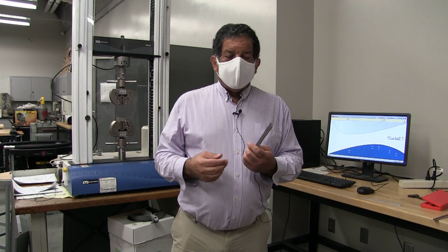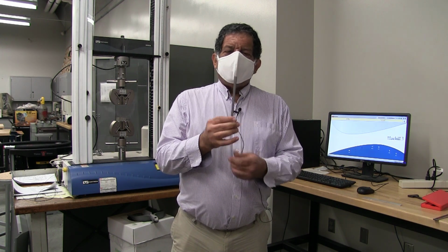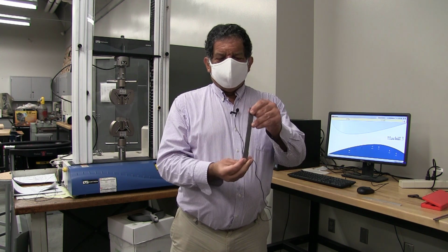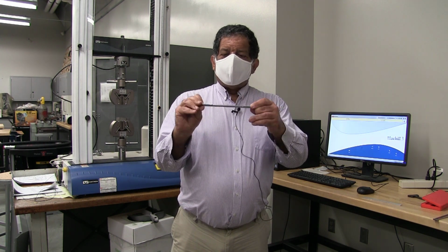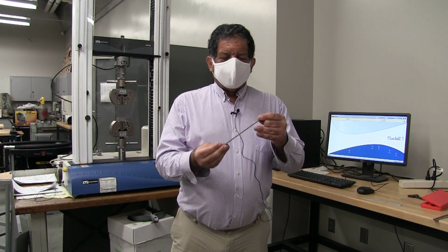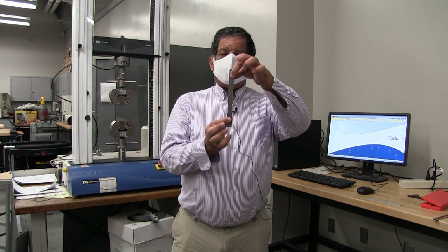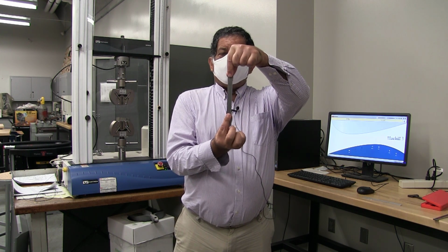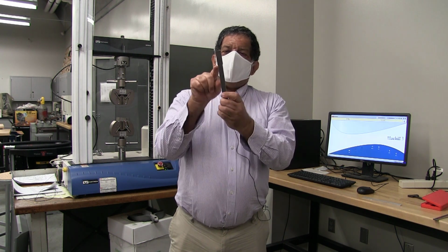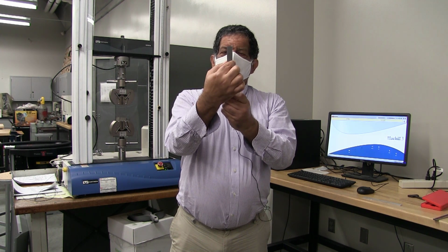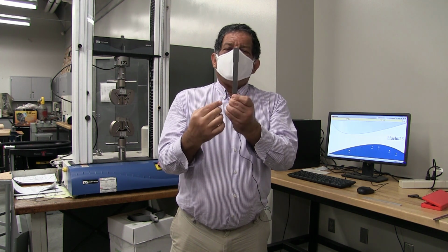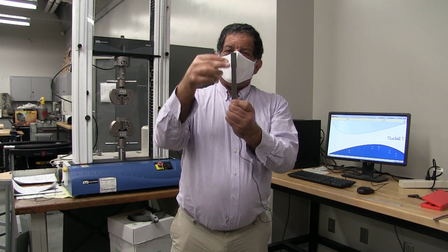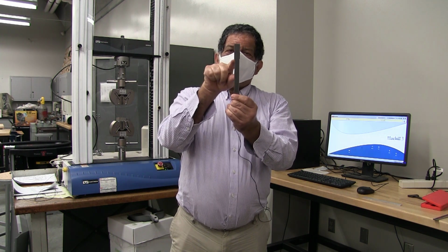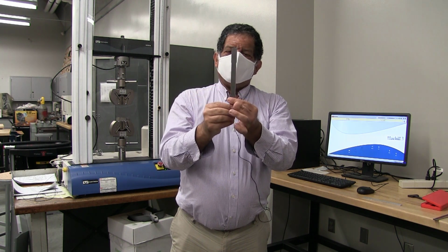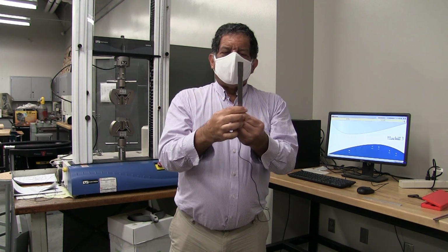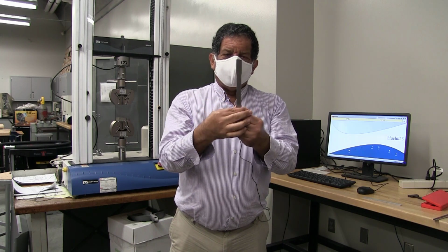The tension test can be done on a variety of kinds of specimens. These particular specimens are flat, as you can see. There's grip areas on the top and the bottom which are going to be placed in wedge grips and grabbed. Then you have a gauge section where the cross section of the specimen has been narrowed in order for most of the deformation to be concentrated over here and not in the grip sections. And you have fillets in the transition between the grip section and the gauge section so that you don't have a sudden change in stress and a stress concentration.